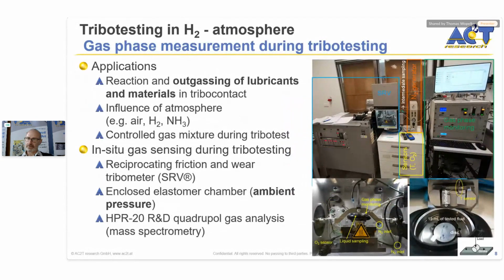The next one is more or less a hydrogen chamber we produced ourselves. Mirko already mentioned it. We use a rubber or elastomer chamber which surrounds the tribo contact, and we mounted this elastomer chamber in an SRV5 tribometer. And since it's a rubber bulk, we can only run it up to ambient pressure, so it's not possible to run it up to high pressure as the tribocell produced by Optimal Instruments.